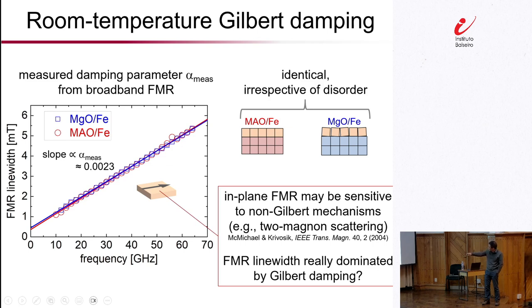So when we are measuring FMR with a sample magnetized within the plane of the film, it turns out that the line width that we're measuring here doesn't necessarily all come from Gilbert damping. There can be other kinds of magnetic relaxation. For those of you quite familiar with NMR, nuclear magnetic resonance, you might be familiar with the T1 type relaxation and T2 type relaxation. Gilbert damping here is analogous to T1 relaxation, whereas there can also be other kinds of relaxation that are kind of like T2 type relaxation processes.